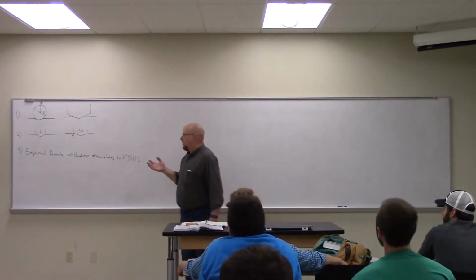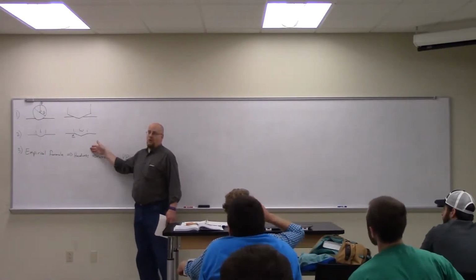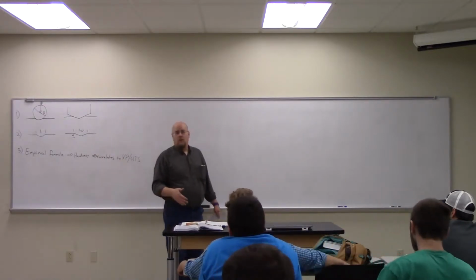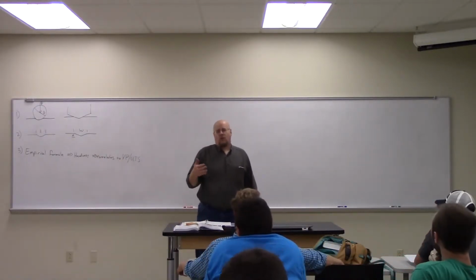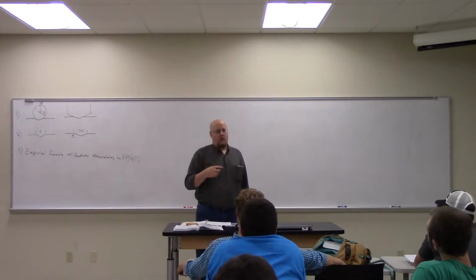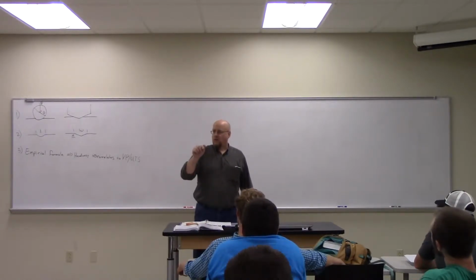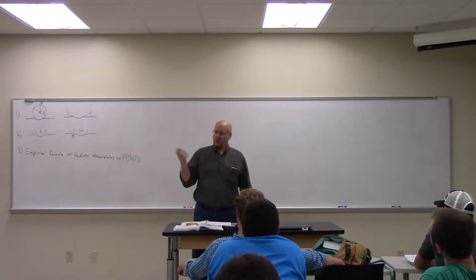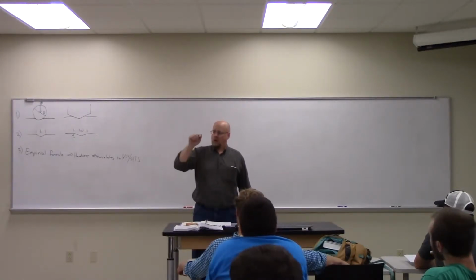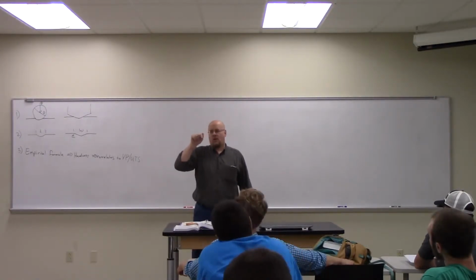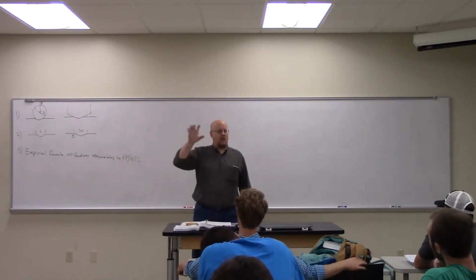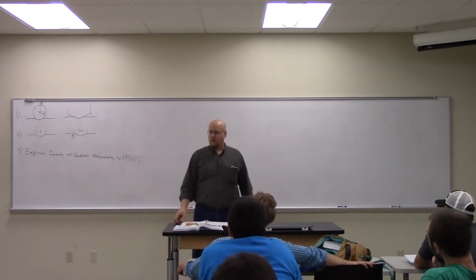Now, the downside to that is I'm only measuring the surface. I'm not measuring what's inside. But it's particularly useful if you've done a weld on an area and you want to see if in the process of welding you've changed the mechanical properties of the steel adjacent to that weld. So you can go in and do these little indents along a radius away from the weld and see how you've altered the mechanical properties.